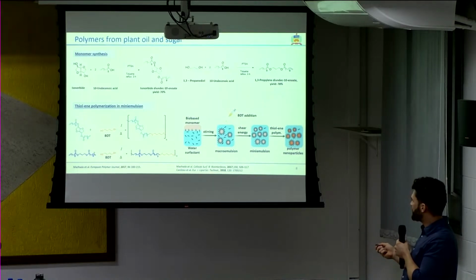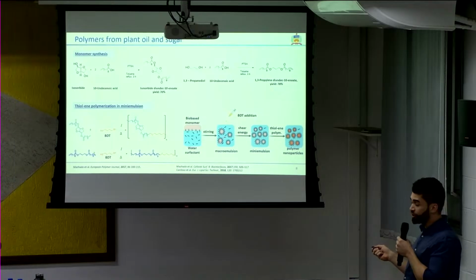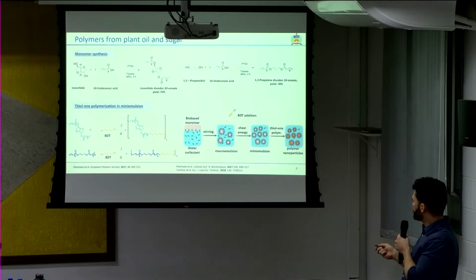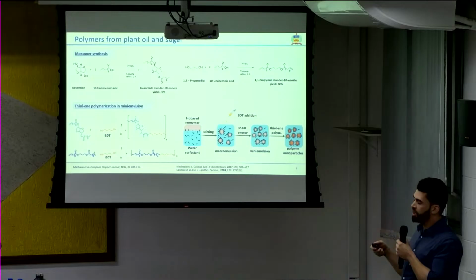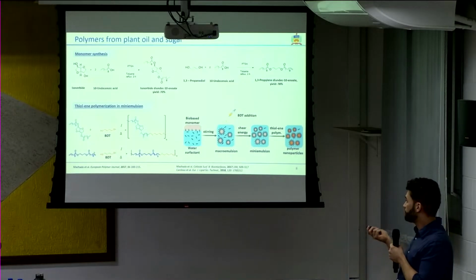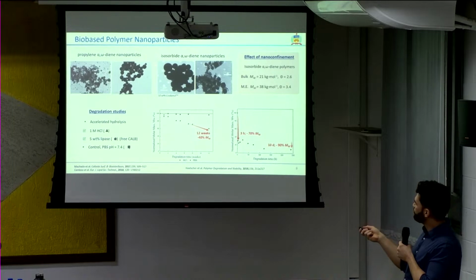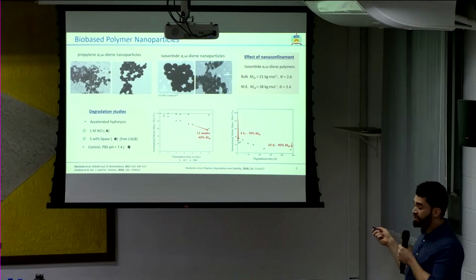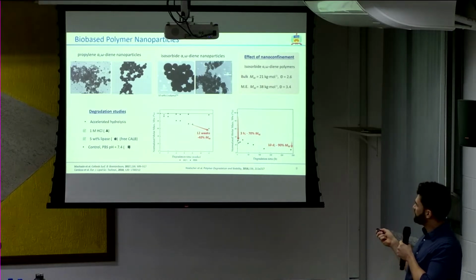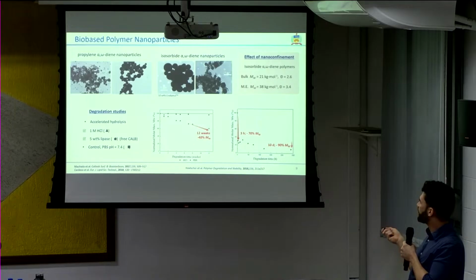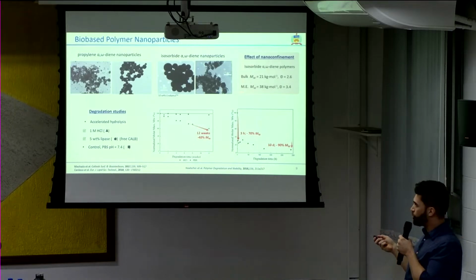And we did this in miniemulsion because we wanted to generate some polymer nanoparticles. So we generate the macroemulsion with stirring, then add the dithiol, input shear energy in the system, have the formation of the miniemulsion, mini nanodroplets, and then thiol-ene polymerization occurs inside the nanodroplets, generating polymer nanoparticles. So here we have the TEM of the polymer nanoparticles, some of the samples that we've made, and we could see that there is some nanoconfinement effect in which the molecular weight of the polymers from miniemulsion are higher than the polymers generated in bulk polymerization.